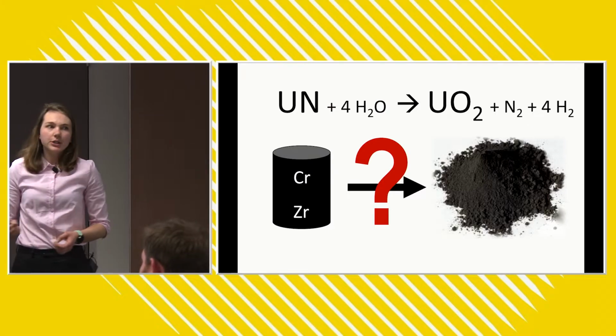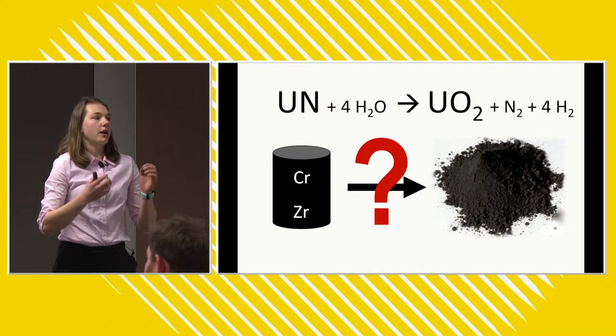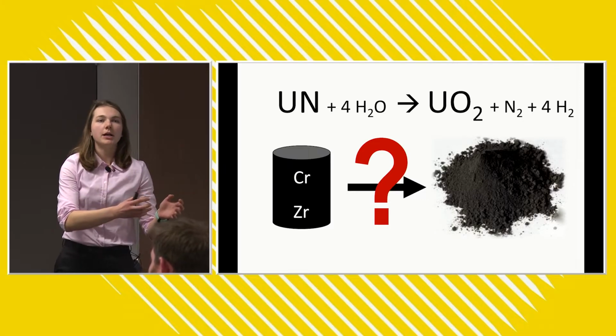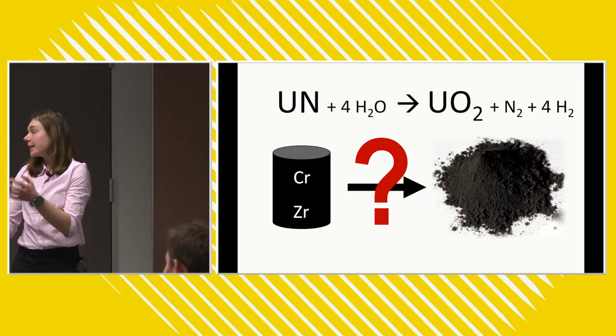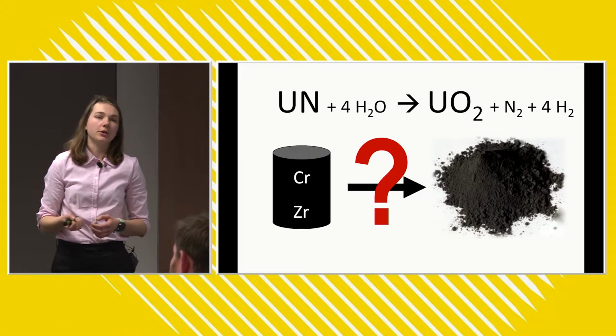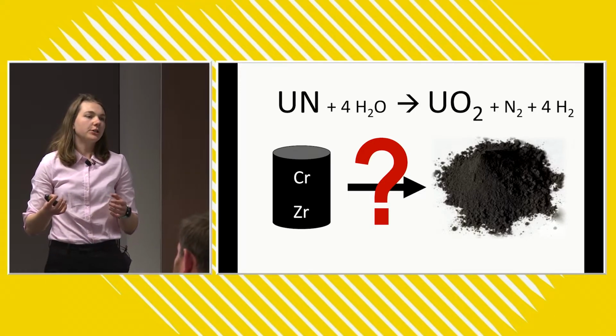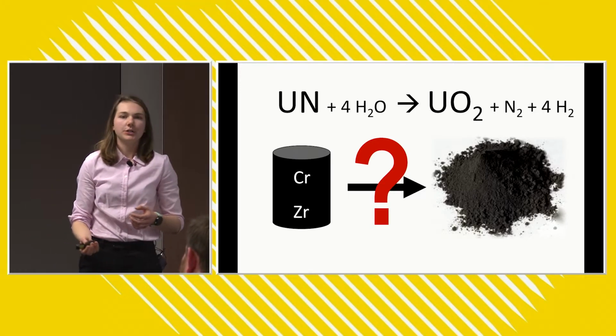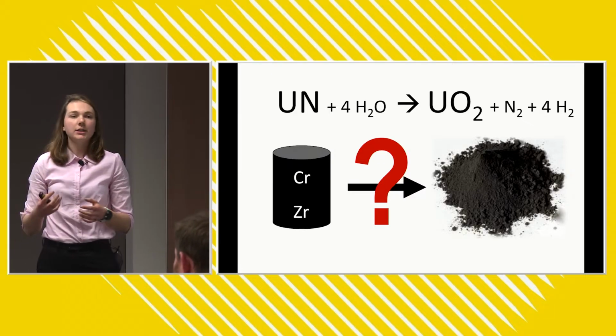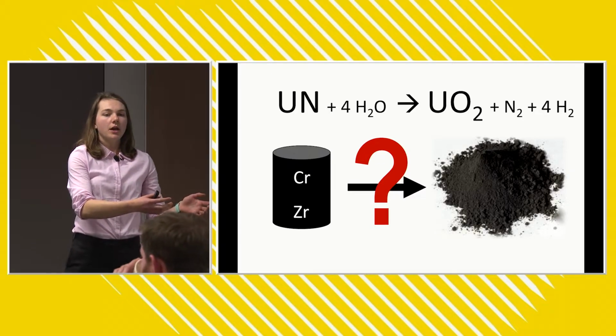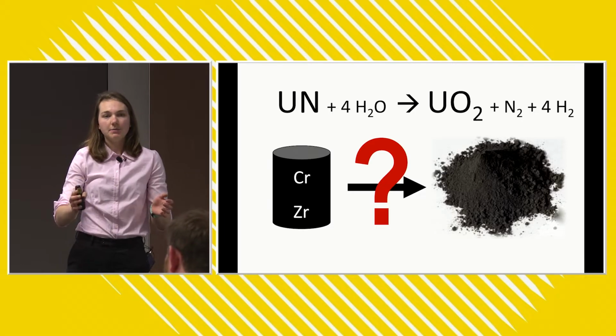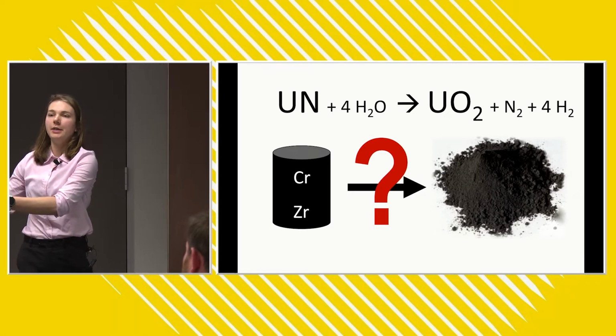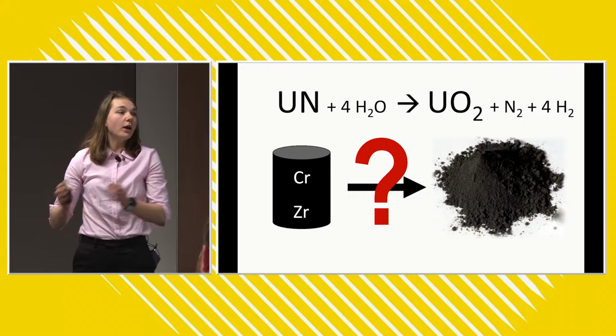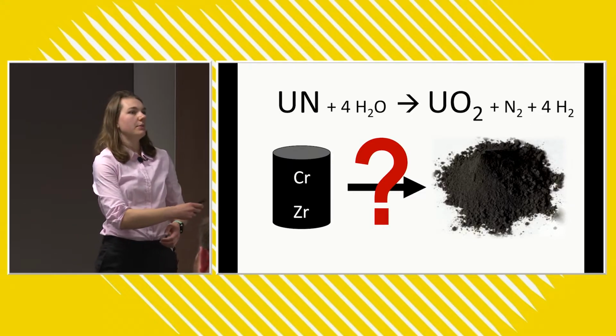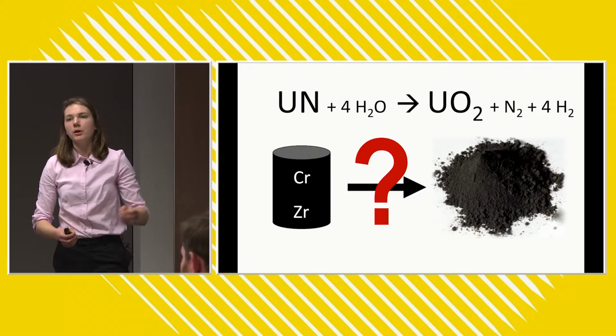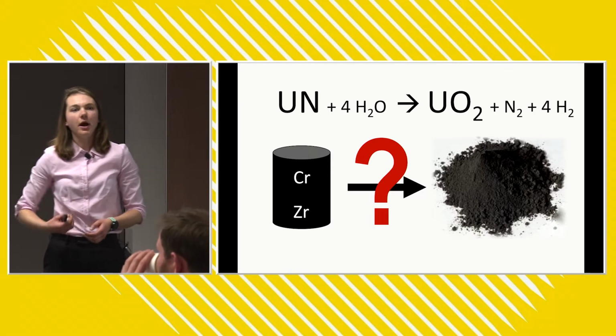So researchers have been able to identify that upon exposure to steam, uranium nitride corrodes, or breaks down, to produce uranium dioxide. And they're able to do this through ex situ characterization. So they can characterize the starting uranium nitride material, subject it to steam, and then characterize the material at the end of the experiment. What is not known is this process in the middle. So how do we get from that start point to the end point? And that's where I come in.